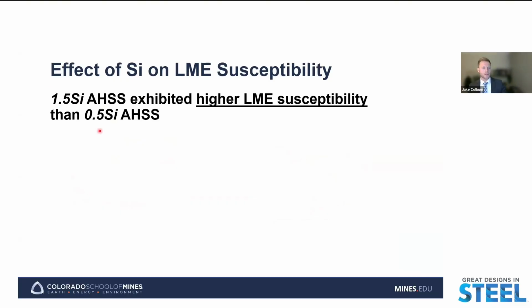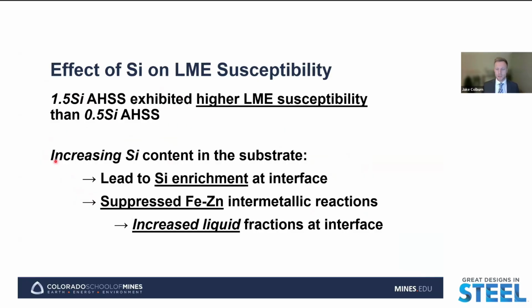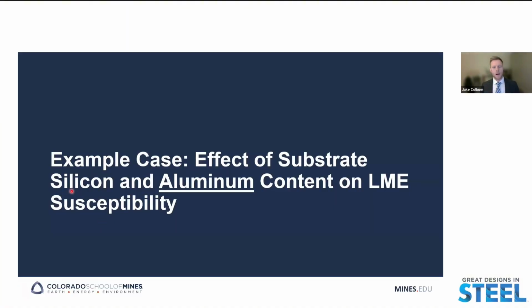And so if we put most of those results together, we can see that the higher silicon-containing steel exhibited higher LME susceptibility than the lower silicon-containing advanced high-strength steel. And we can attribute much of that to saying that if there's an increasing silicon content at the interface, we saw silicon enrichment present at the interface that also then led to suppression of the iron-zinc intermetallic reaction, specifically that gamma phase. And overall, that then leads to increased liquid fractions or increased liquid availability at the interface and therefore increased LME susceptibility. And so now we're going to take a look.